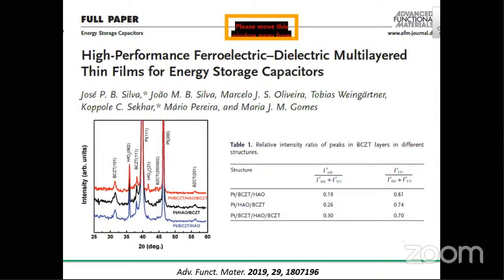Here we have deposited only 150 nanometer thickness, so we used this grazing incidence X-ray diffraction pattern. When you observe these XRD peaks, we have BCZT 101 and BCZT 111 peaks. Here I tried to calculate their intensities. When you observe this table, these are the peaks related to BCZT. What we observed here is that PT BCZT HAO has 0.81 orientation of 1-1-1. That means it has a highly epitaxial nature, oriented in the 1-1-1 direction. In principle, it should have better properties.